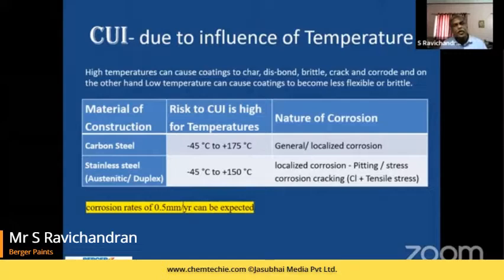The corrosion rate has gone to more than 0.5 millimeter per year, more than what is expected. And the coatings which are present now are getting disbonded. They become brittle, they crack, and they allow the corrosion to pass under the insulation in a very severe way. In the case of lower temperatures, the coatings become less flexible, and therefore less able to protect. So in both the cases of higher temperature and lower temperature, corrosion under insulation has to be handled with a point of view.